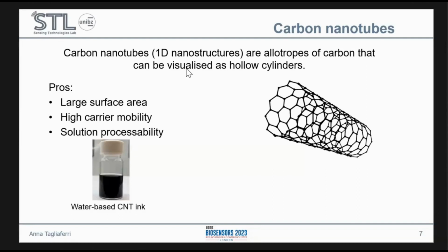The large area allows for a large number of biorecognition elements to be attached to them, helping us in improving the sensitivity of the devices. They also exhibit high carrier mobility, which makes them excellent semiconductor materials for our purposes. Moreover, they are easily processable in solution with the addition of a surfactant, such as carboxymethyl cellulose or sodium dodecyl sulfate. And this here is an example of one of our water-based carbon nanotube inks that we used for the spray coating deposition, that I will also explain later.